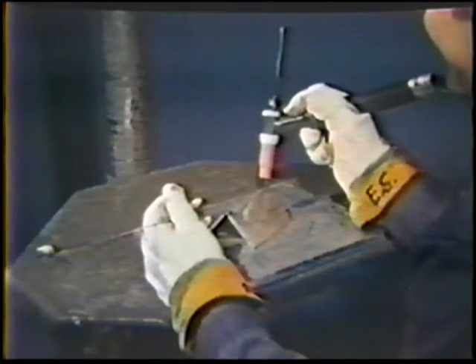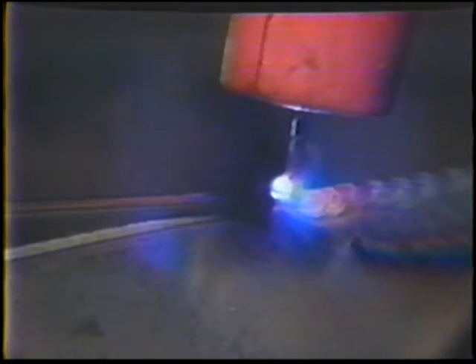Start the arc and form the puddle. On the high pulse, hold the torch steady to obtain fusion. On the low pulse, move the torch forward for 1/2 of the puddle diameter to allow the puddle to cool slightly. The finished bead will appear similar to the weld produced without pulsation, except that the ripple will be more pronounced on the face. Inspect the weld, and then continue practice.